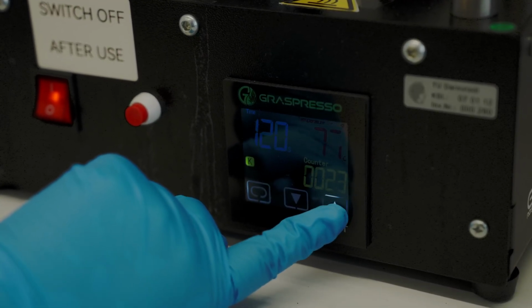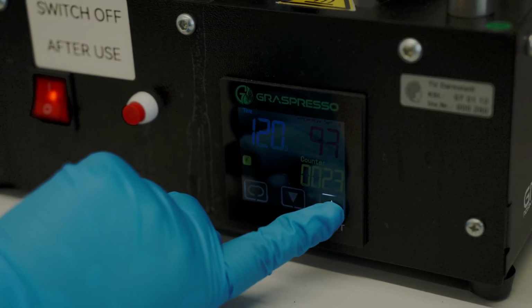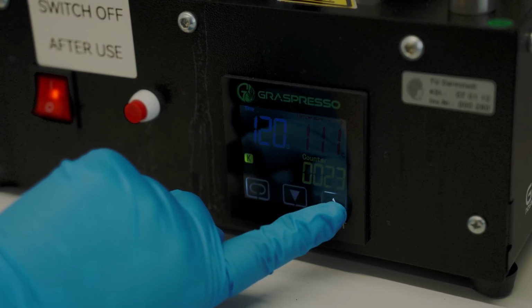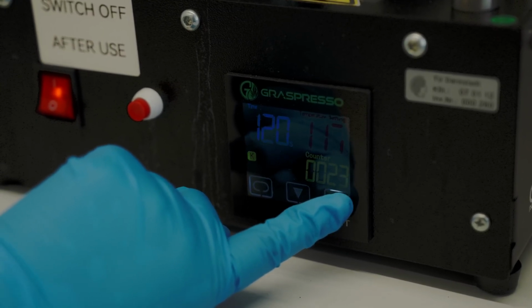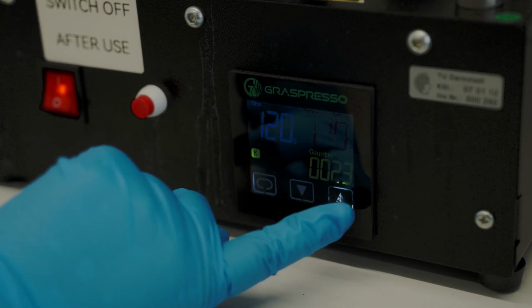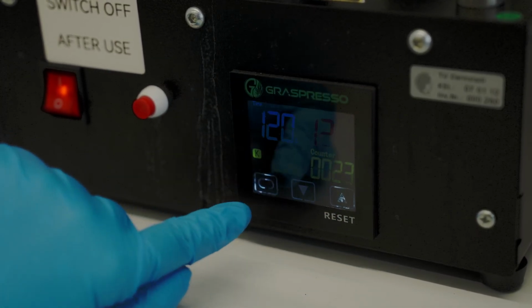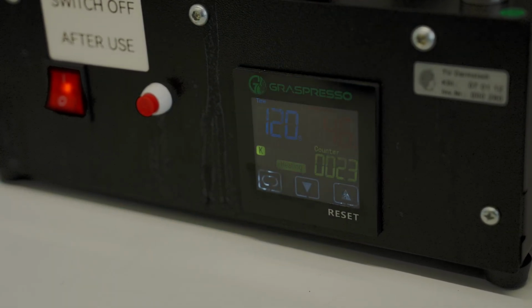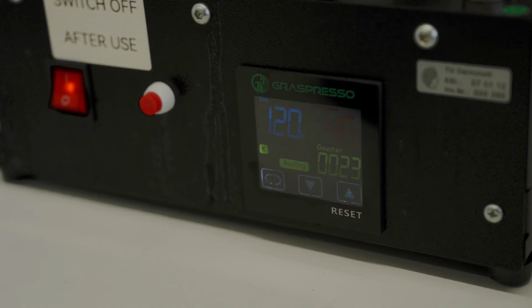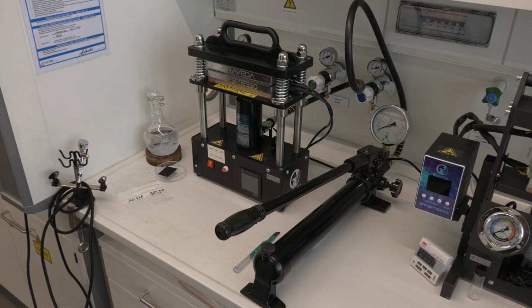The system takes approximately 4-5 minutes to reach 120 degrees Celsius, followed by a 2 minute dwell time. Cooling down to 40-45 degrees Celsius takes up to 1 hour. Once cooled, the press is opened and the membrane electrode assemblies are ready for testing.